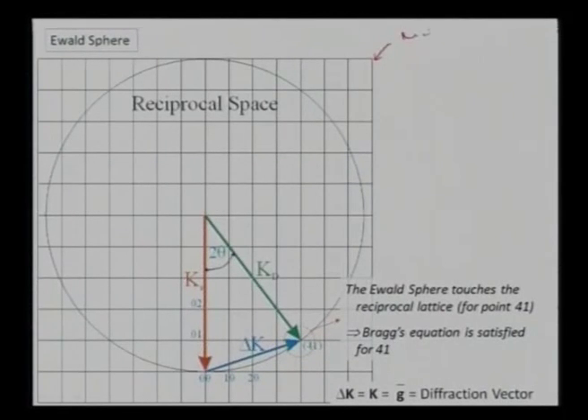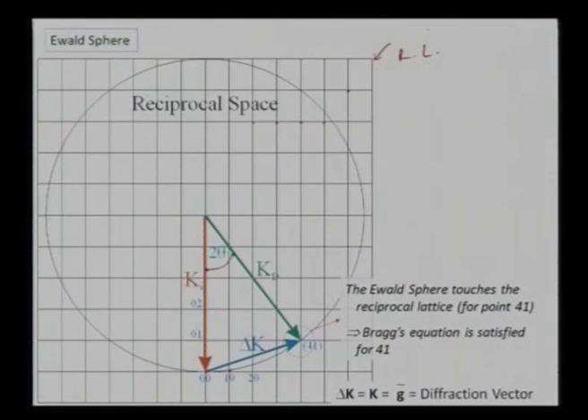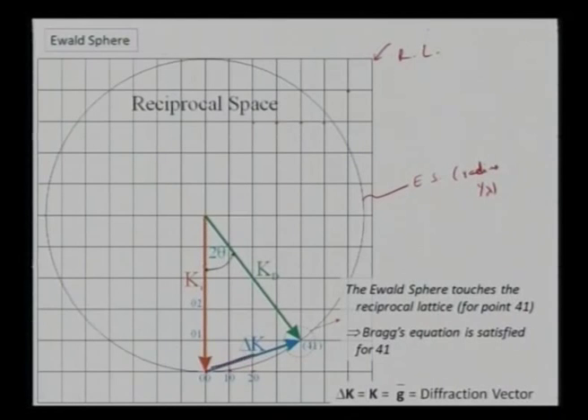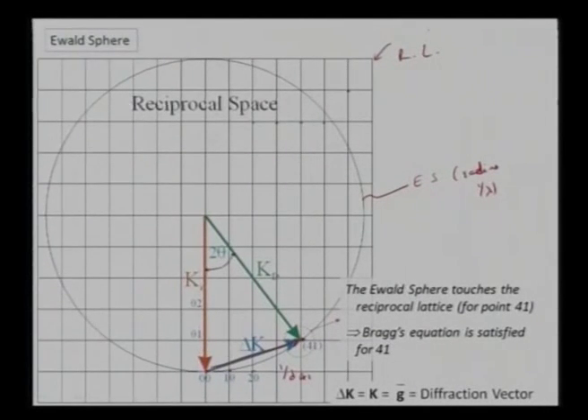In the construction of reciprocal space I have my reciprocal lattice — individual planes can be represented by all the intersection points. I have a 2D reciprocal lattice: 0 0 1, 0 2 0, 0 3 0 and so on. My Ewald sphere has a radius of 1/λ. When a particular point touches the Ewald sphere — say 1/d of the 4 1 plane in 2D — the Ewald sphere of radius 1/λ is satisfied, and the 4 1 plane's condition is met, producing a diffraction spot.